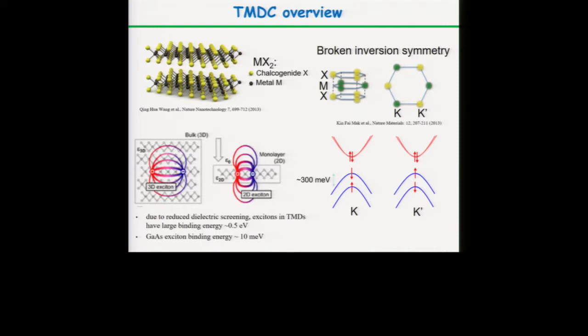Another important optical property of these TMDCs is that they are a truly 2-dimensional semiconductor. There is reduced dielectric screening, and if you shine light on them, you can create excitons, a truly 2-dimensional exciton, compared to gallium arsenide, which is really a 3-dimensional semiconductor. As a point of comparison, the binding energy for an exciton in a TMDC is around 300 to 500 millielectron volts, compared to the binding energy of an exciton in gallium arsenide, which is only a few millielectron volts. So you need to cool down gallium arsenide in order to see excitons, whereas in TMDCs you can see them at room temperature.